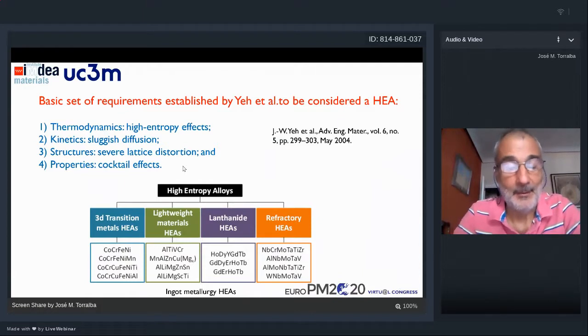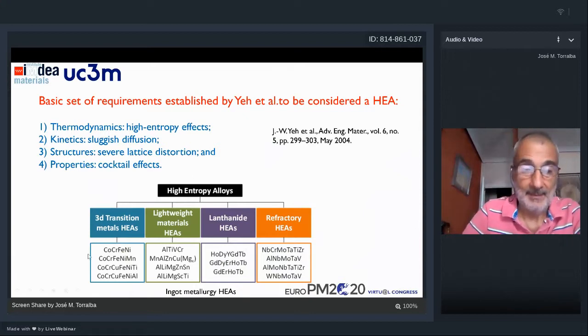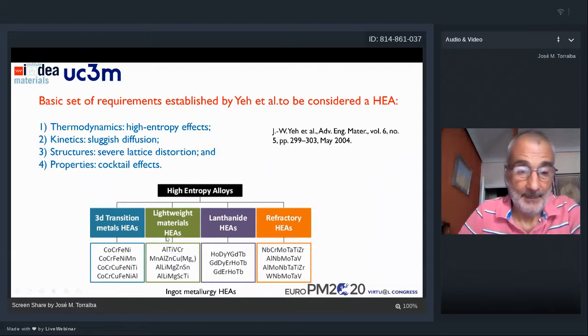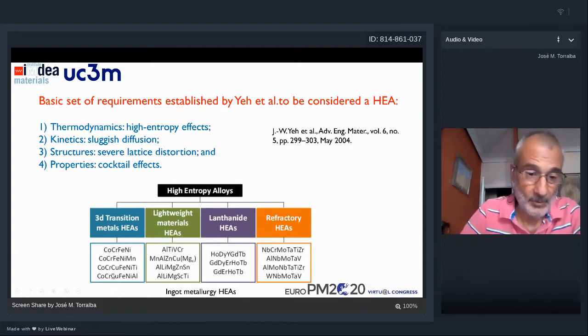If we consider the conventional ingot metallurgy high entropy alloys, we can classify them especially in 2 main groups. One group is the so-called 3D transition metals. The other group is the refractory metals. So we have this kind of high entropy alloys and these other refractory high entropy alloys. And there are another 2 groups in which some light metal materials like aluminum or titanium are included. Most of these high entropy alloys are small variations from those.